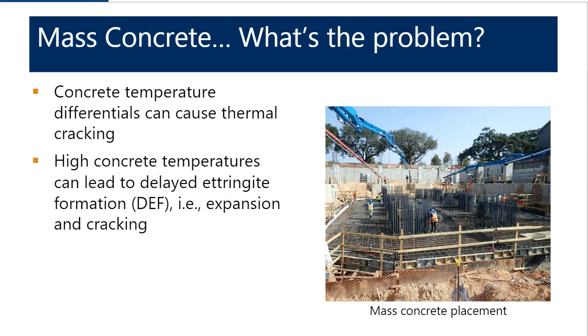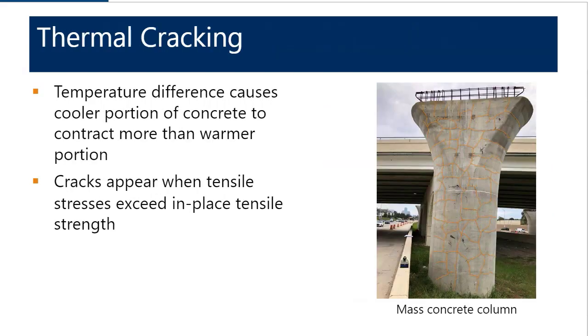So let's talk about thermal cracking. How does that occur? And so here's a column, 8 foot in diameter, that had thermal cracks shortly after it was placed. The cooler surface of the concrete can contract relative to the warmer inner core of the concrete. And as a result, you end up with tensile stresses along the surface. And when those tensile stresses on the surface exceed the in-place tensile strength, you can get cracking.